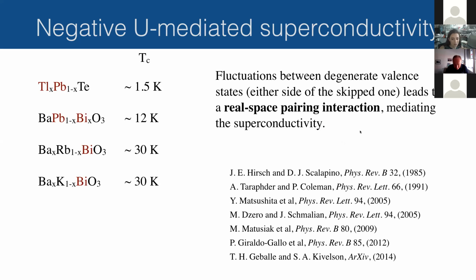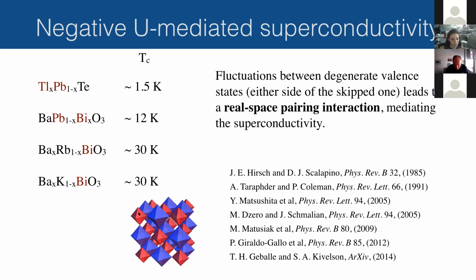So why is this relevant for nickelates? Well, here is the sketch of the nickelate insulating state again. Remember, it is disproportionated. At least you can see clearly here that it is bond disproportionated, but it is also charge disproportionated. So the thought was that maybe the charge disproportionation here is similar to the charge disproportionation that you get in these negative U insulators. But probably what is important is, again, that you have fluctuations. We know that nickelates are like this, just insulating, and people have tried to dope nickelates, but they're not getting superconductivity. So there's something else.